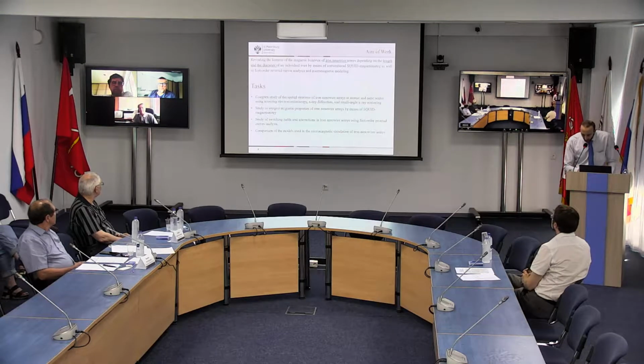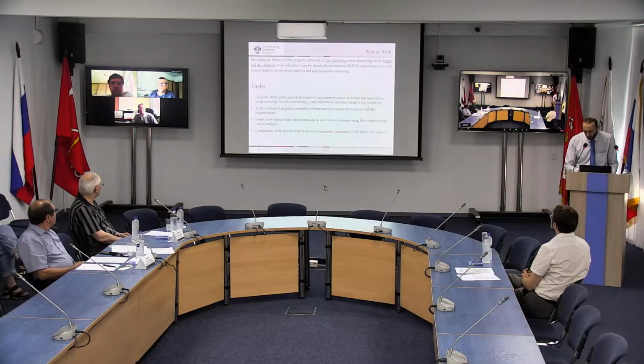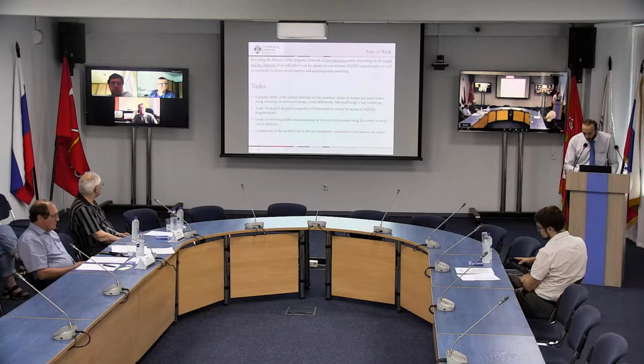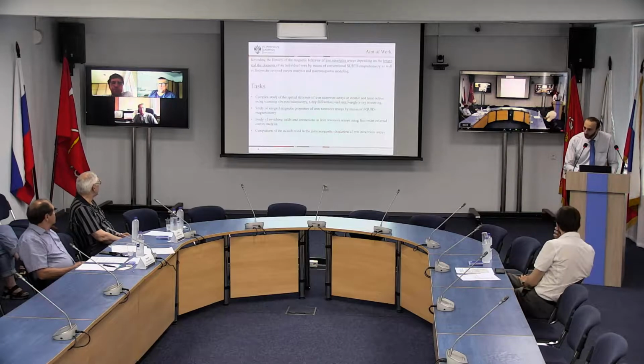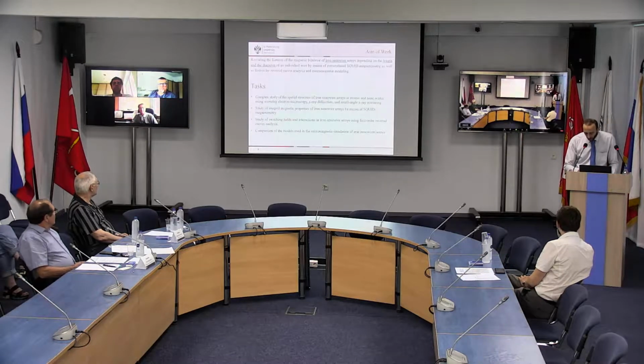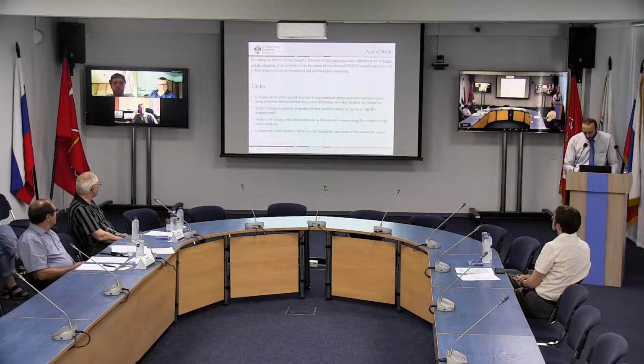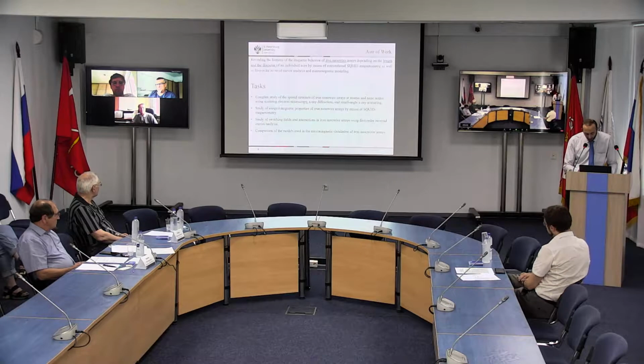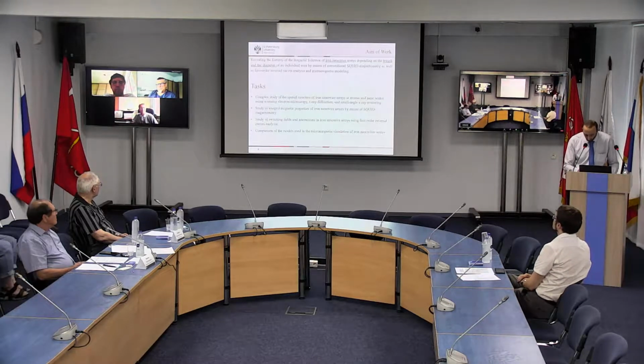In order to reach this goal, we have performed a complex study of the spatial structure of the array at the atomic and nanoscales by using scanning electron microscope, X-ray diffraction, also small angle X-ray scattering. We also studied integral magnetic properties of iron nanowire arrays by means of SQUID magnetometry. Also we studied switching fields and interaction in the array by using FORC analysis, and compared the models used in micromagnetic simulation of iron nanowire arrays.